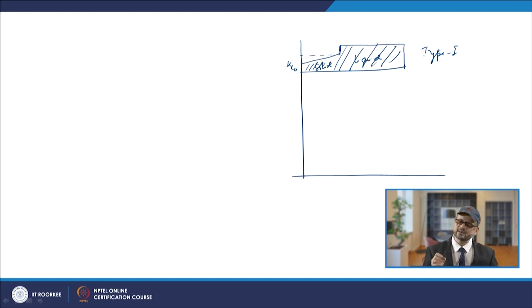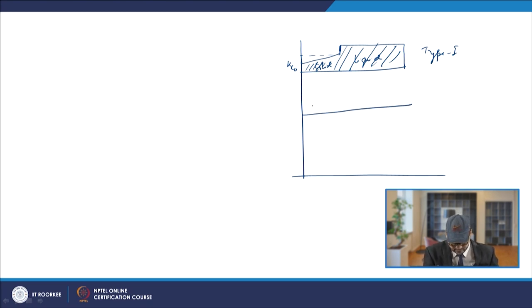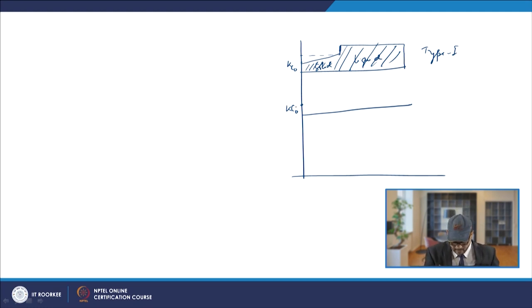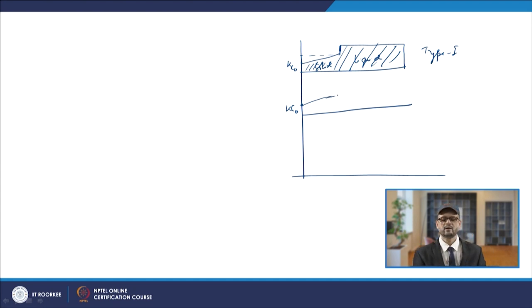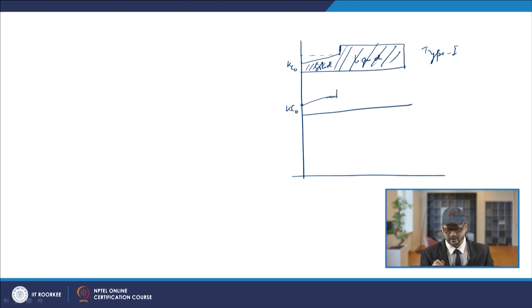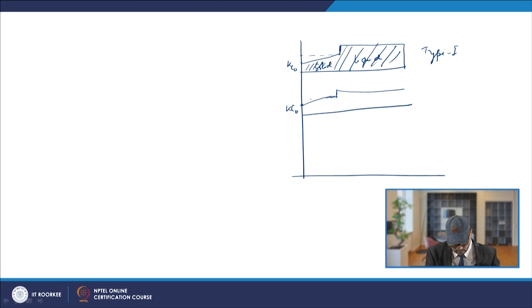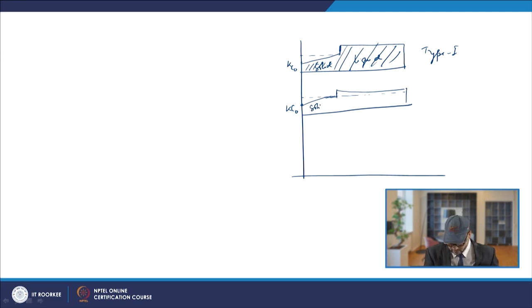If you have limited liquid diffusion, what you see is that from C0 in the solid, the concentration comes up and there will be some pile-up. Then the profile drops back, with some increase above C0 due to the limited diffusion in the liquid creating a solute-enriched boundary layer ahead of the interface.